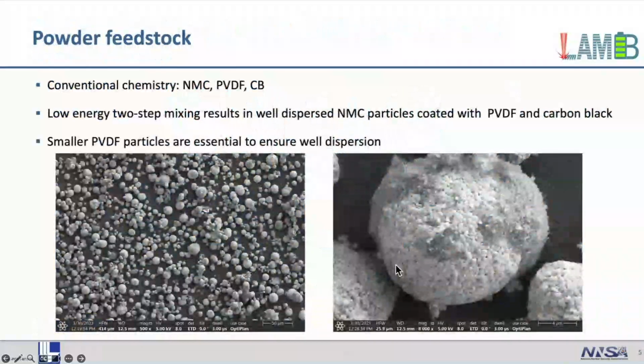So this is how it looks from the powder feedstock. Conventional chemistry using some developed two-step mixing approach. These SEM images show how uniform it is. And from this zoomed-in image, you can see those PVDF and carbon black coated on the NMC polycrystal particles there.